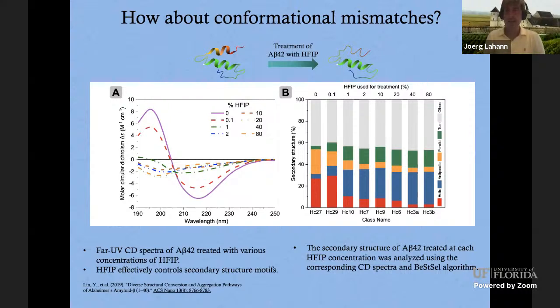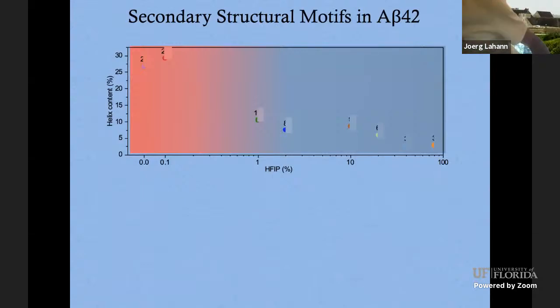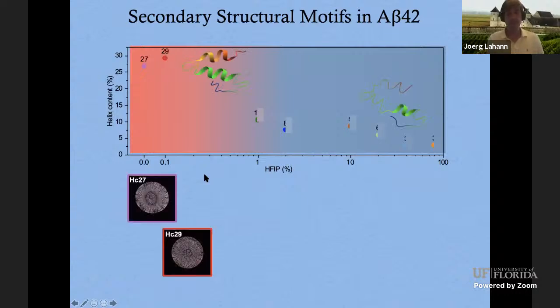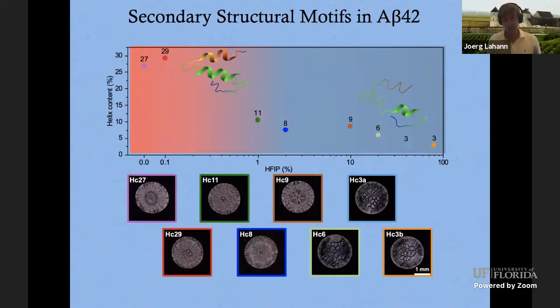Now, that's okay, but the question is whether this is maintained when we put it back into a normal buffer system. And so we treated this for 15 minutes, took it back into our buffer system, and then measured the CD data that you see and the alpha helix and beta sheet content in that particular buffer. And that works actually quite well. And you can see that we can change this systematically here, and then you see the droplets that we created. The number here is always the helical content of the peptide. So the higher the helical content, the more normally structured the peptide is. As we go to helical contents below 10, for instance, it becomes quite disordered.